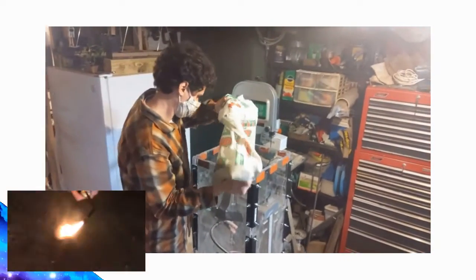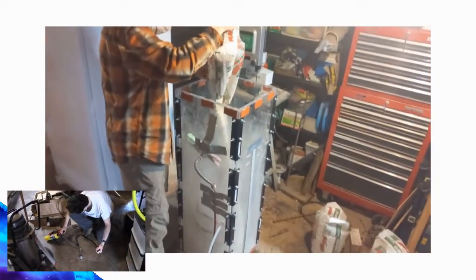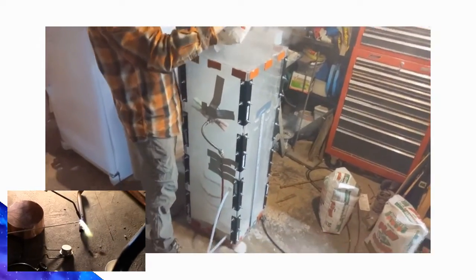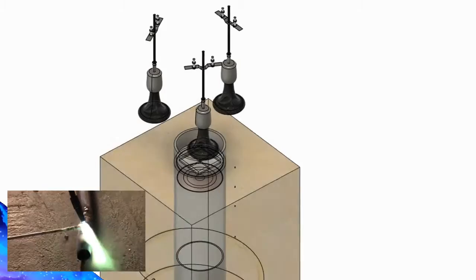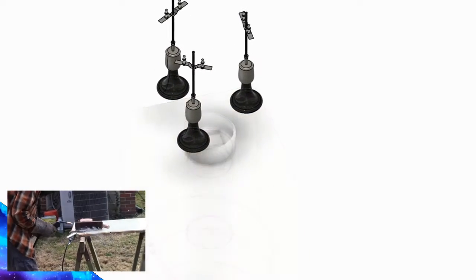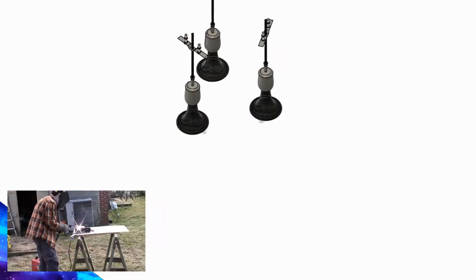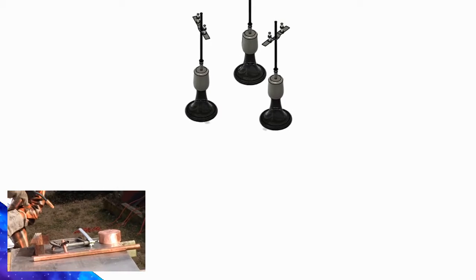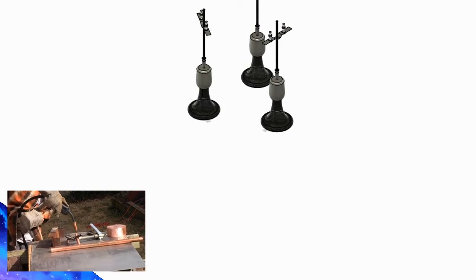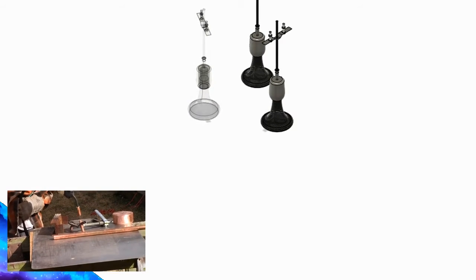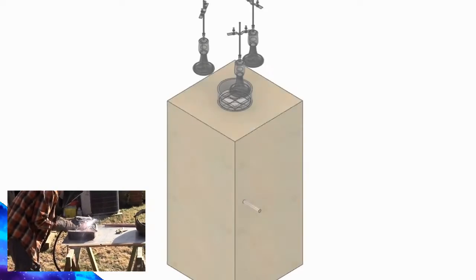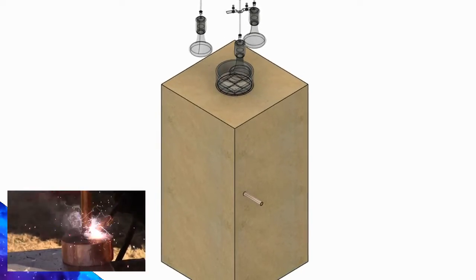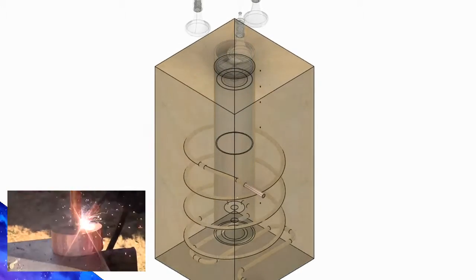To simulate lunar soil, the box was filled with sand to a depth of 75 centimeters. Sand was chosen over other possible simulants, such as sawdust, because of its availability and known thermal properties that are similar to actual lunar soil. To simulate solar radiation, 3 250-watt heat lamps were hung 5 inches above the sand. For the 750-watt test, all 3 heat lamps were used, and for the 500-watt test, only 2 of the heat lamps were used.